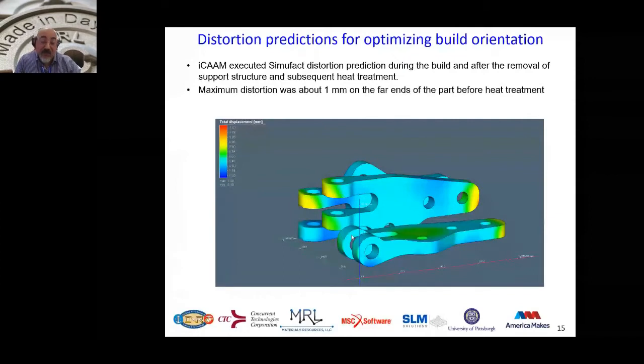We covered the 360-degree available orientation, but from those selections, we were able to predict that the maximum distortion in one of them was about 1 millimeter, but we were able to get the part to have the least amount of distortion as well as the least amount of machining required, and that's the part in the middle. That's what you saw in the prior slides, how we are able to build it.